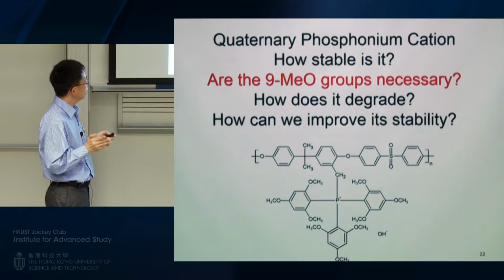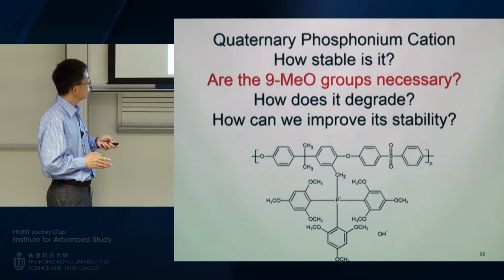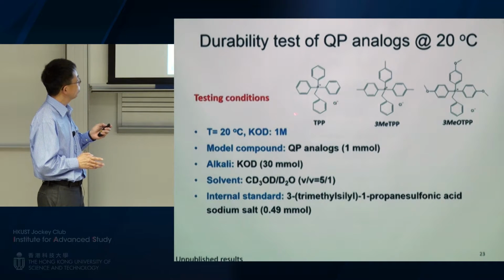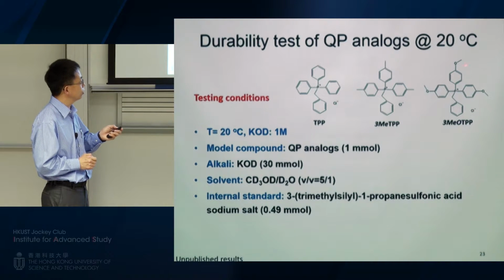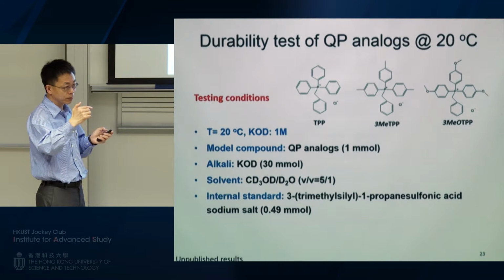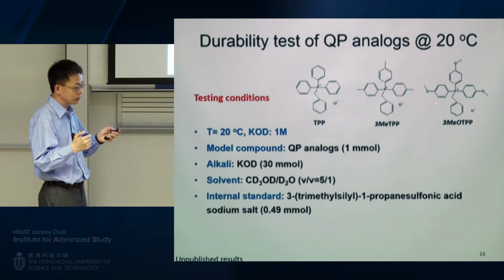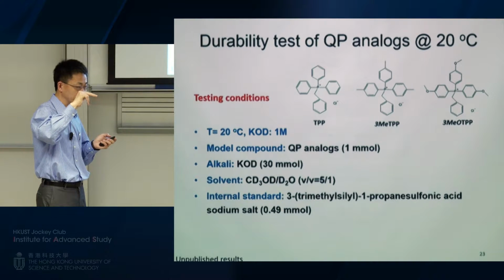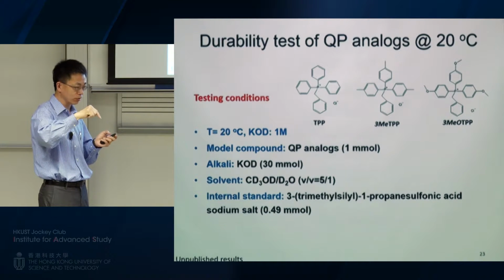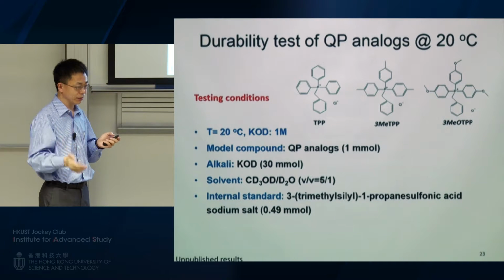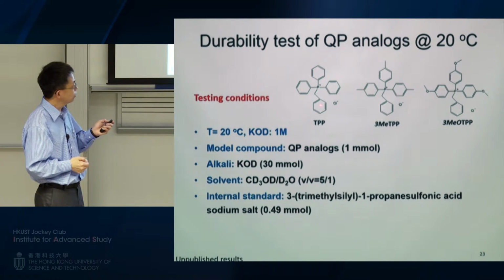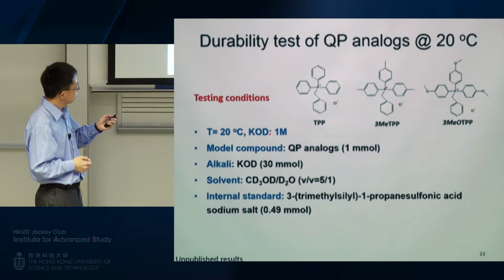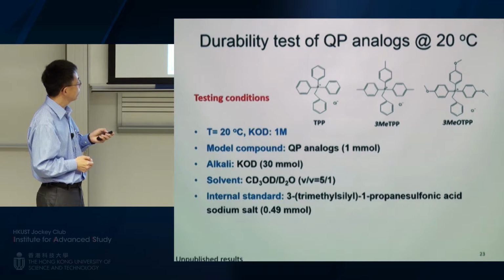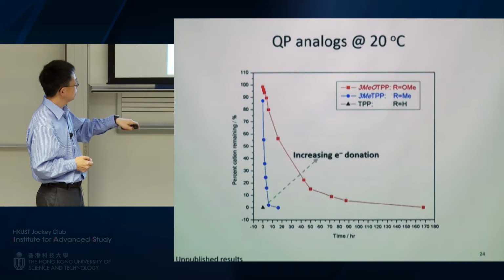So the next question is, are the 9 methoxy groups necessary? So we started saying, okay, what if we don't put any substitution? What if we put 3 methyl groups? What if we put 3 methoxy groups, but not 9? And I have a list of 6 methoxy groups, and we actually changed the methoxy groups' position, from para, meta, ortho, and I'm going to skip all that in my student's thesis, just showing you these 3 simple molecules. If you look at the testing conditions, they're the same. So what we found was very interesting.